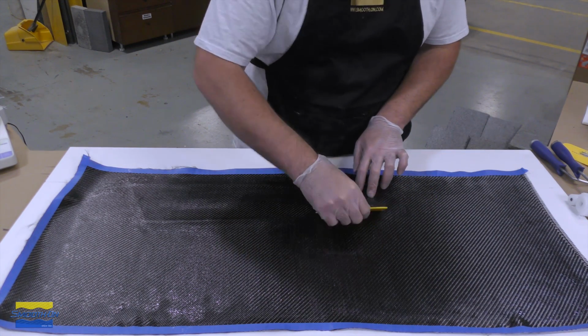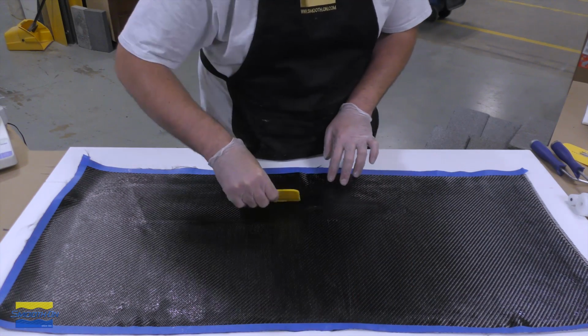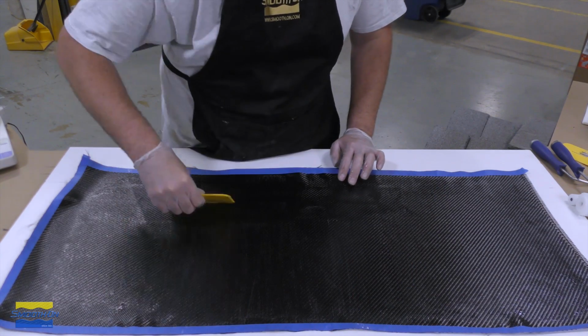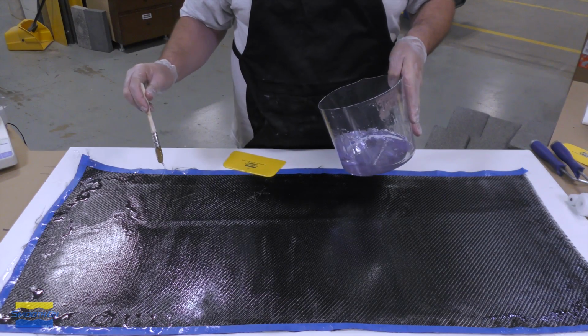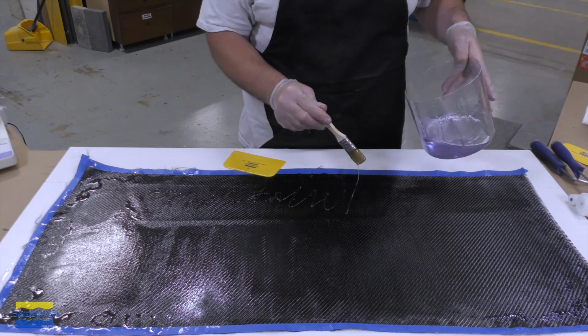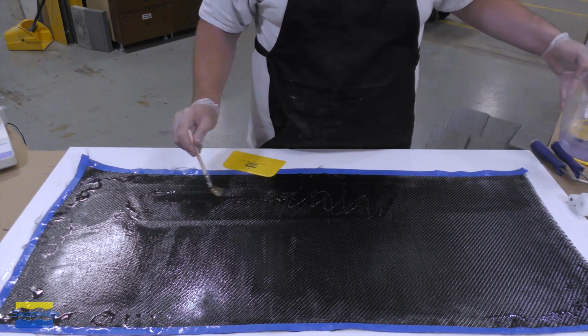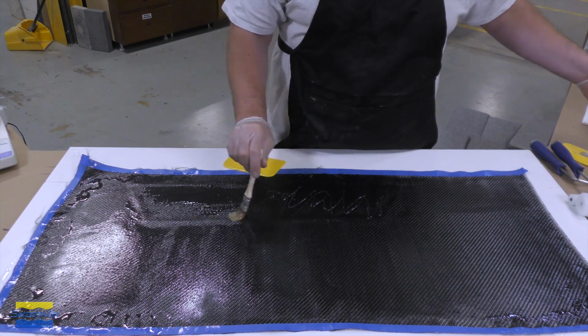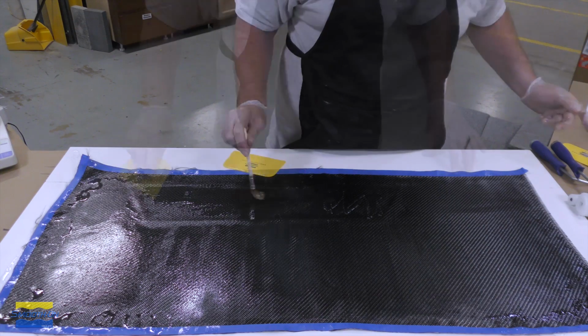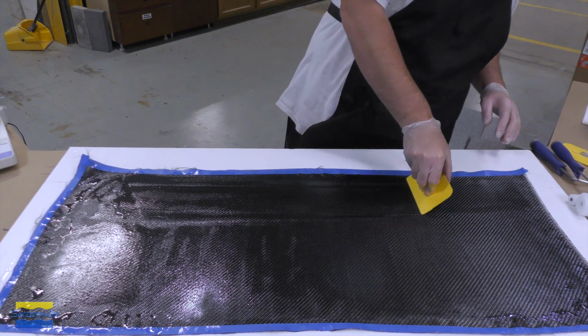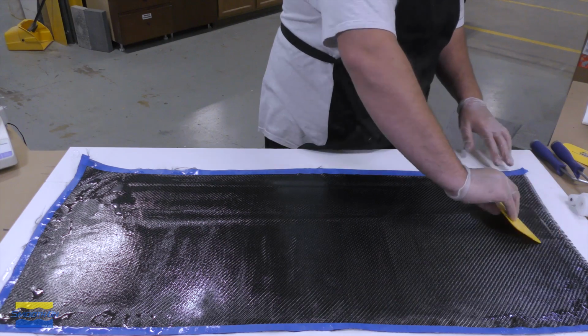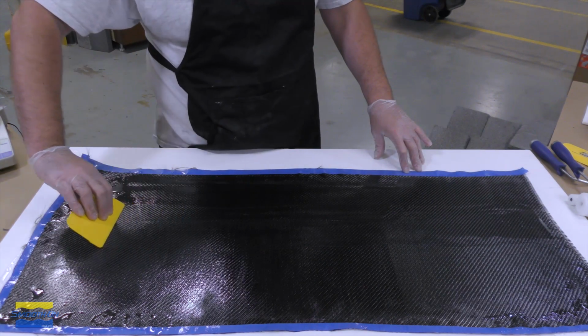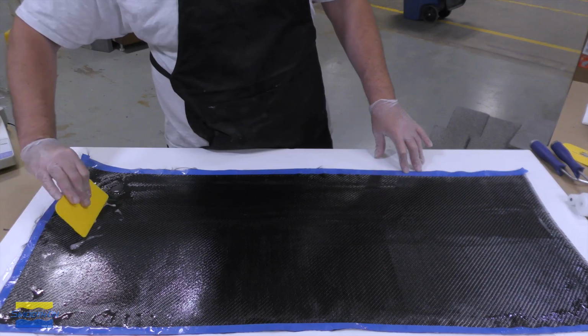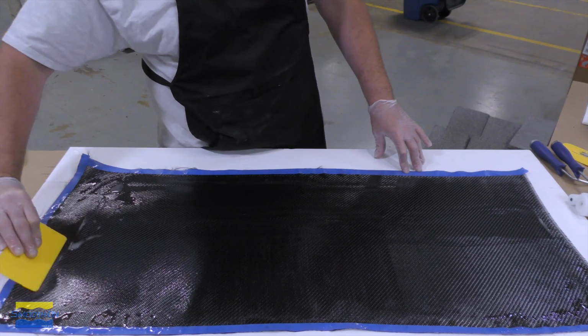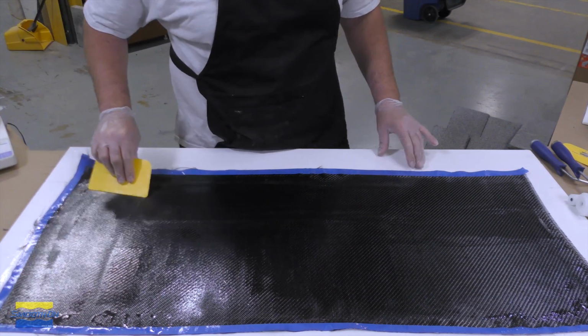Now we're going to use a squeegee tool and we're going to basically push the epoxy through the cloth. This is called impregnating the cloth. Keep in mind that the epoxies are exothermic, and that means that the more mass you have in the mixing container, the faster it's going to set off and start to react, generating heat. So if you don't anticipate using the material fast, make sure you transfer it into a larger container or something where the material is not as mass concentrated.